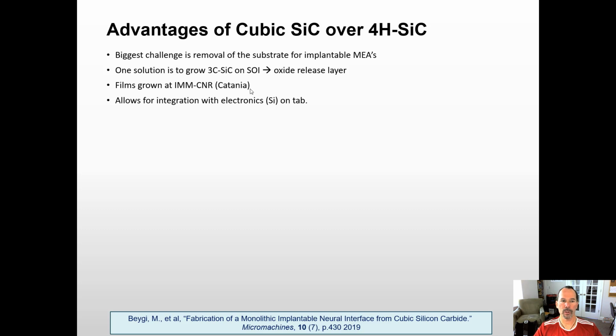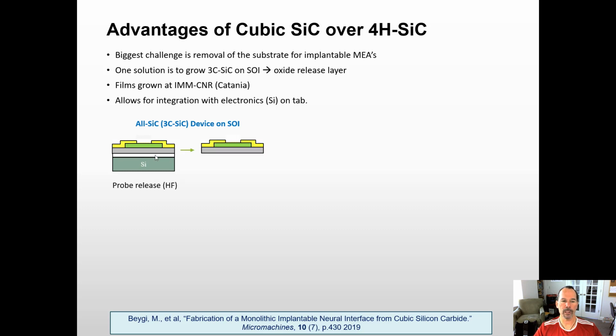Our films were grown in Catania, Sicily, through a collaboration I've had for nearly 2 decades. And what this also allows us to do is integrate electronics onto the tab outside of the brain, preamplifiers and so on. So this opens up a whole area of technology that we can use because we're using semiconductors for our device. Same idea, we have our PN junction, only now it's on SOI. Here's oxide, there's a thin silicon layer here. And so we make our device, we release with HF.